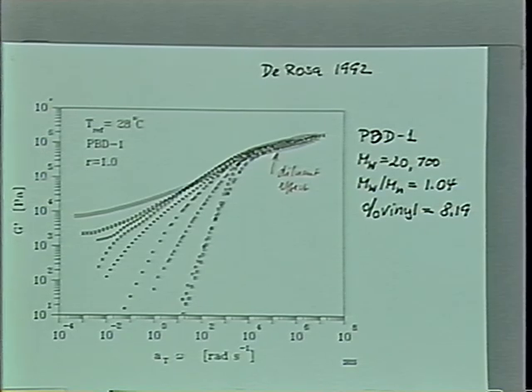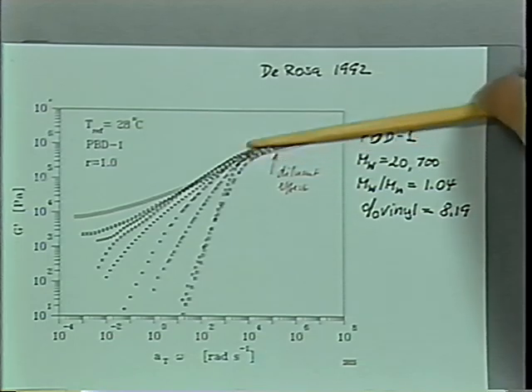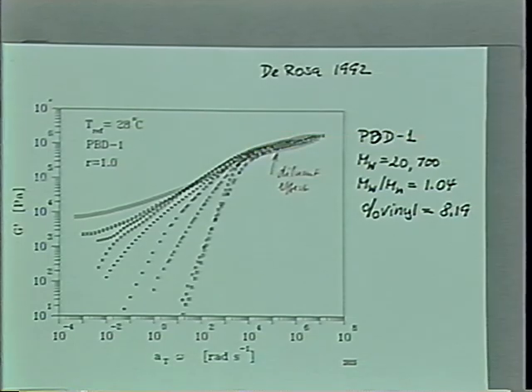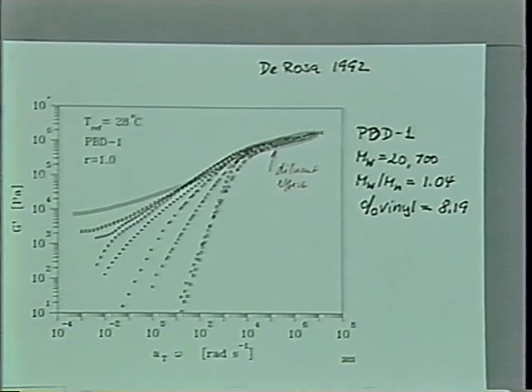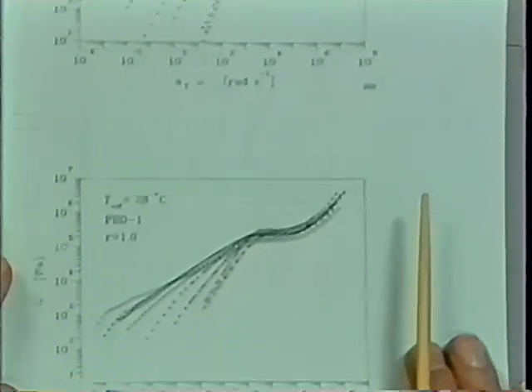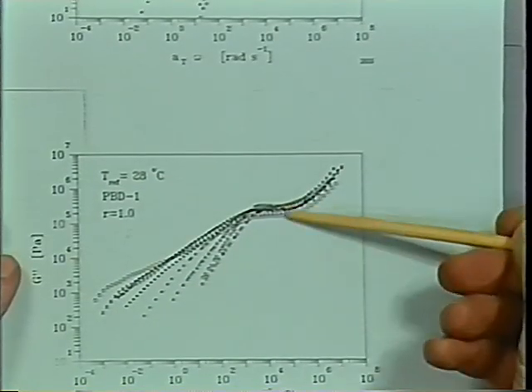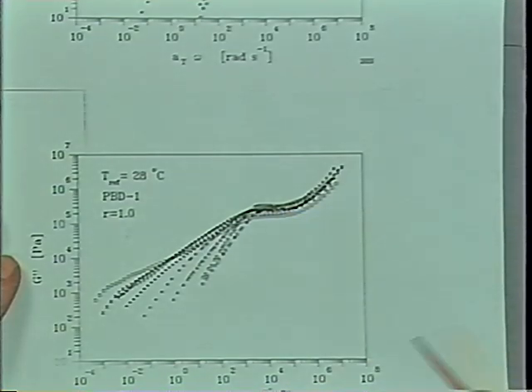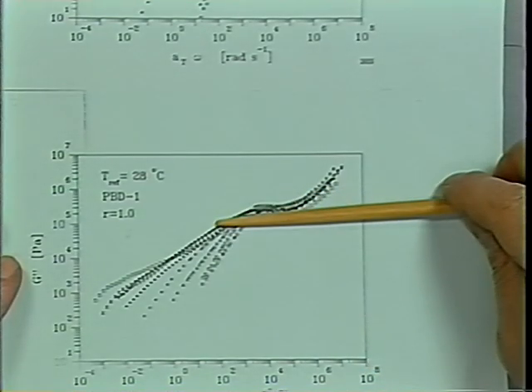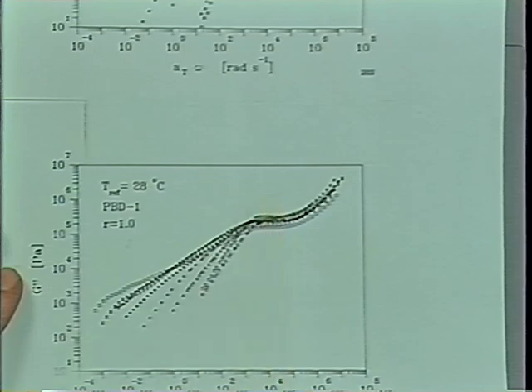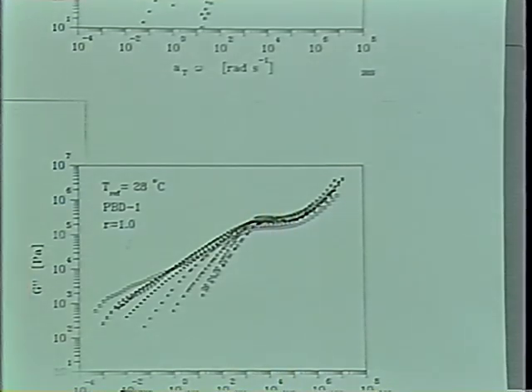But somehow the general feature of the behavior in the entanglement region doesn't seem to be changed by the introduction of cross-links. Here for G double prime, you see also the effect of solvents. A solvent basically reduces the spectrum, puts it further down, and changes the characteristic time to a shorter value, to a higher frequency in this case.